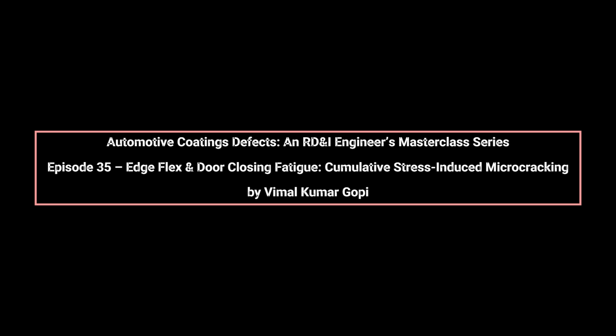Environmental exposure accelerates fatigue degradation. Temperature fluctuations change substrate dimensions, increasing strain amplitude during door movement. Moisture ingress through early microcracks promotes hydrolysis and plasticization, further weakening polymer chains. In cold climates, reduced polymer mobility increases brittleness, making fatigue cracking more severe.